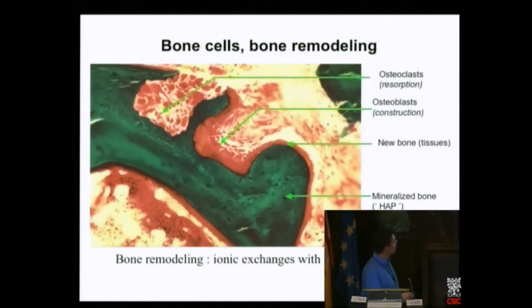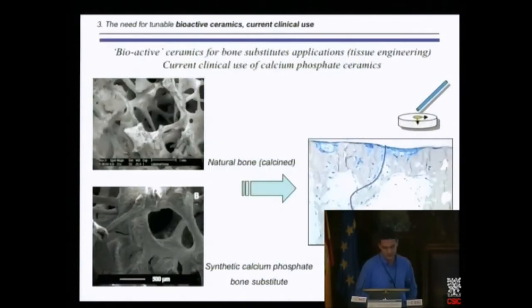And after this bone resorption, you have other cells that are responsible for bone reconstruction. So after resorption by some cells, there is a reconstruction with other cells, which are called osteoblasts. So here is a new bone, which is highly rich in collagen, in organic phase, which has been reconstructed by these cells. So of course, you have to take into account the activity of these cells versus your new material for bone substitution. And especially for bone remodeling, we need ionic exchanges with body fluid, especially calcium and phosphate. So that's why we use calcium phosphate ceramics and glasses.